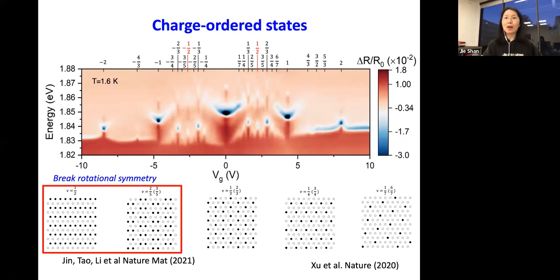Yeah. So of course, I did not tell you the entire story of what's going on here. Under certain approximations, you can think of the amount of blue shift as sort of proportional to the gap size. So those different states have different gap sizes. For example, 1/3 and 2/3 have the largest gap size for those fractional filling states. And ν equals zero has, of course, the largest gap in the system. And the Mott insulating state has the next largest gap. But this is monotonic, but it's not linear. It's a very, very slow change.